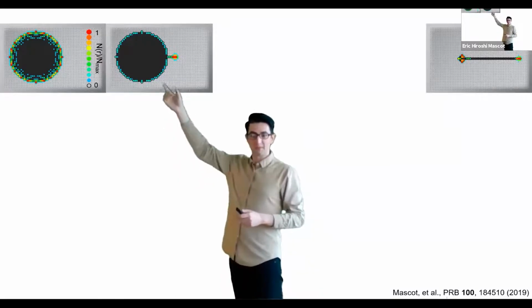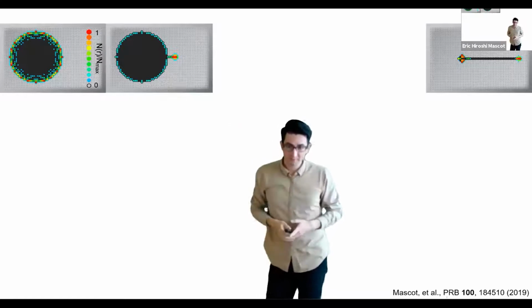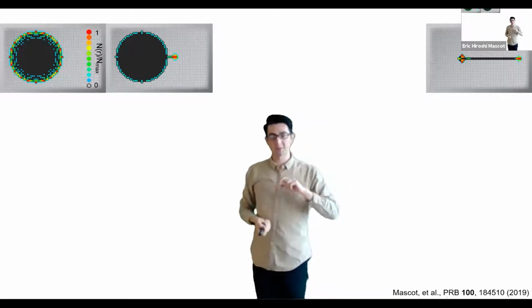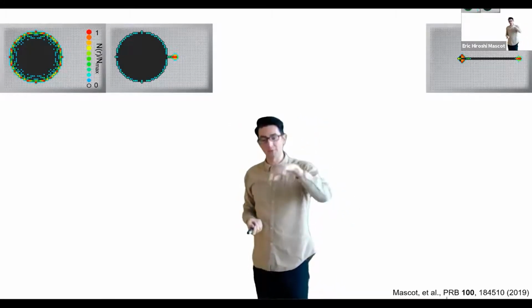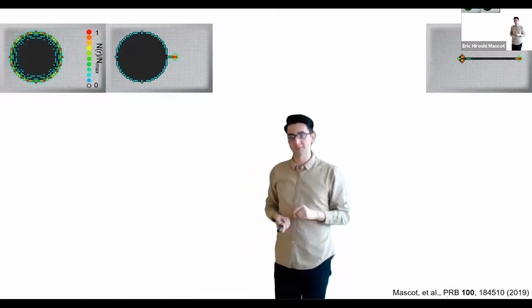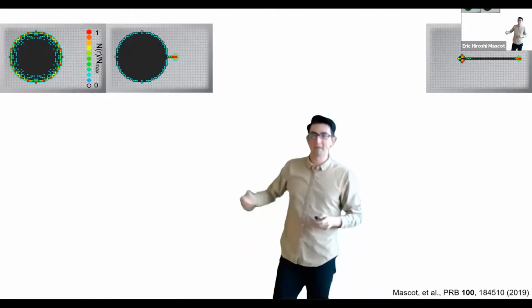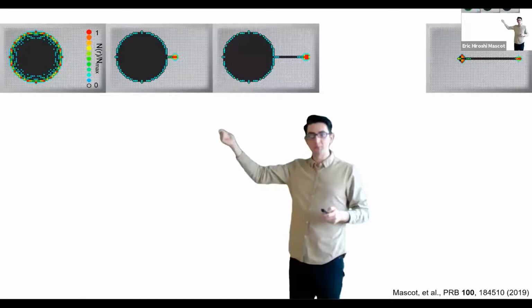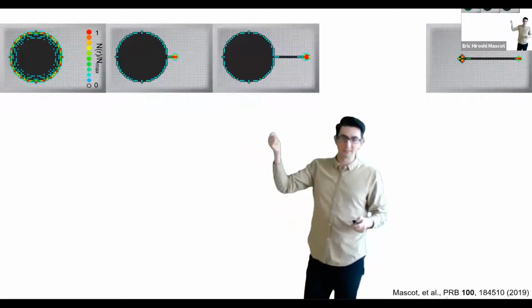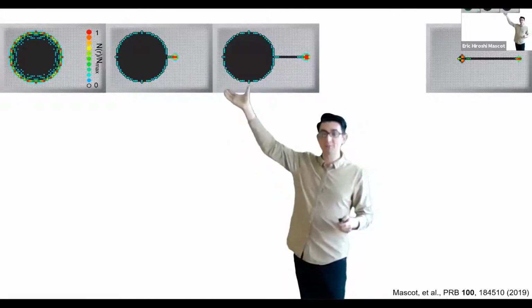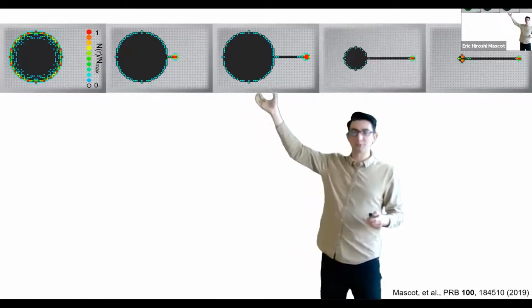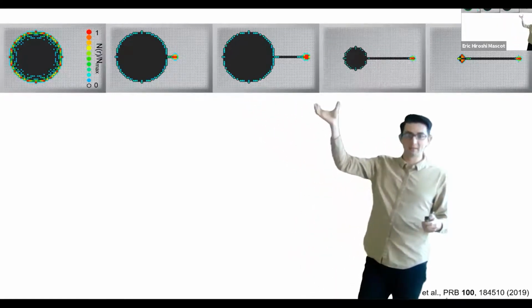So here we're adding single magnetic adatoms. And you can do this with atomic manipulation techniques where you can drag and drop single iron atoms to the island. And by attaching this chain, we're pulling out a Majorana bound state. And this chiral Majorana edge mode is here. And if we shrink that island, it turns into a Majorana bound state.